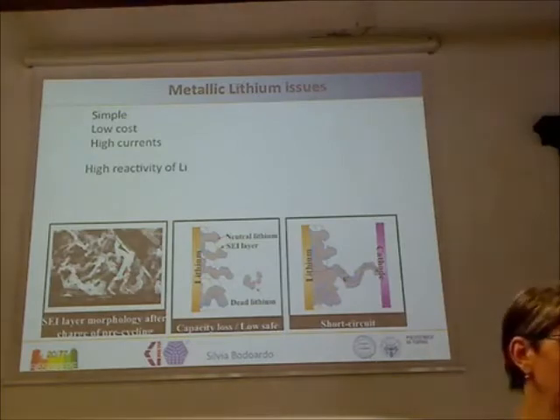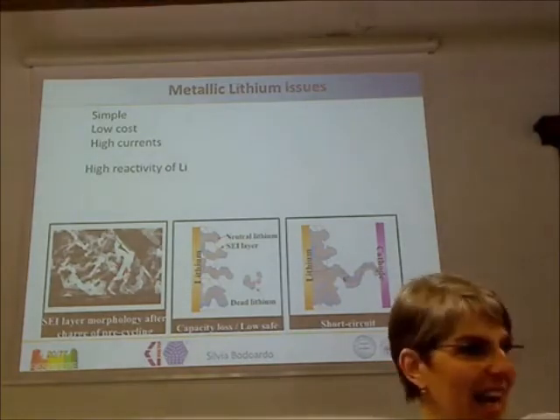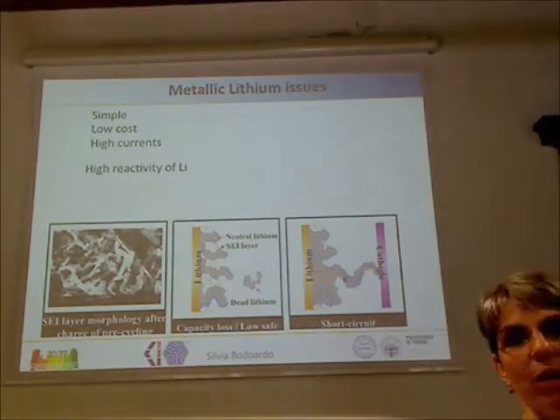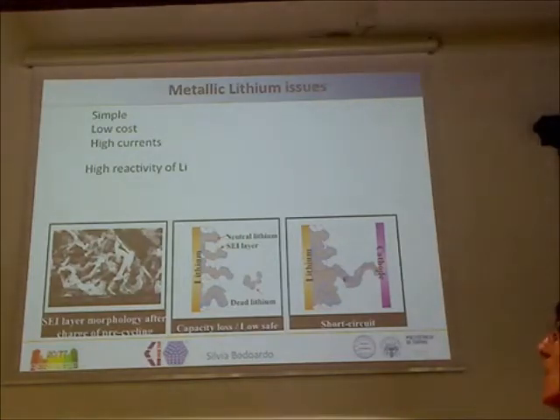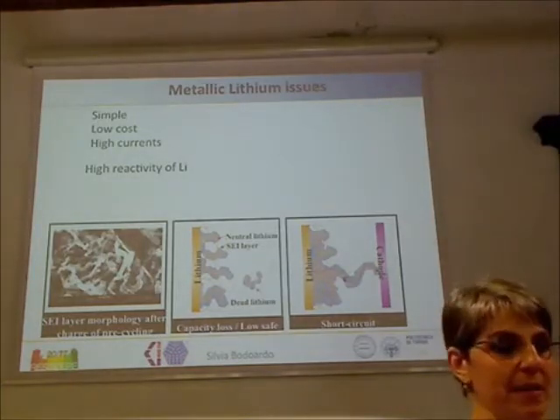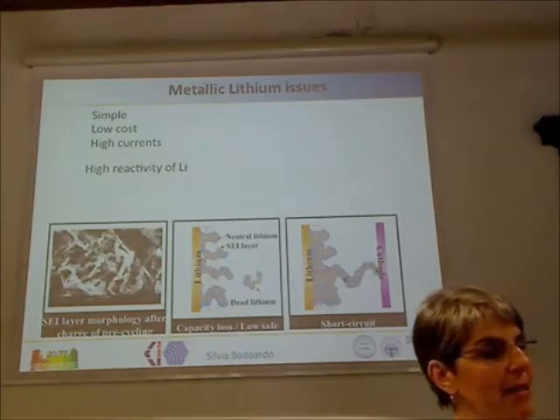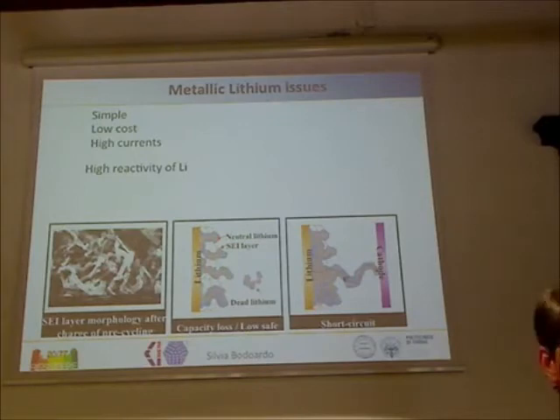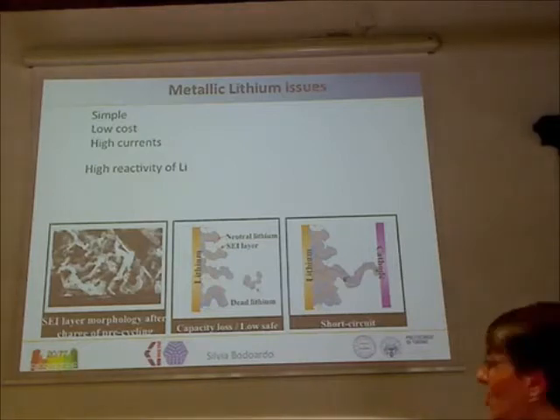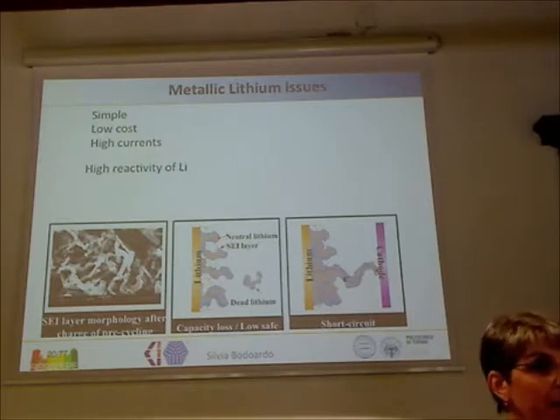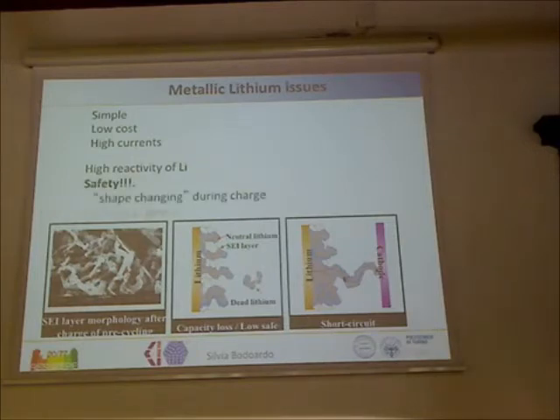But it is highly reactive. You know that, due to its very low reduction potential, it reacts very quickly with water, giving explosive reactions with oxygen, nitrogen, and everything you have in the air. And moreover, during the charge and discharge processes, when lithium reduces on its surface, it doesn't form again a plane surface, but it starts growing, forming this kind of dendrites that can leave the electrodes, for example, forming some dead lithium, or can also cross the cell, short-circuiting the cell. And so this is a big problem, because in this case you can get really a very unsafe system. For this, really, safety is a problem, as I told you before.